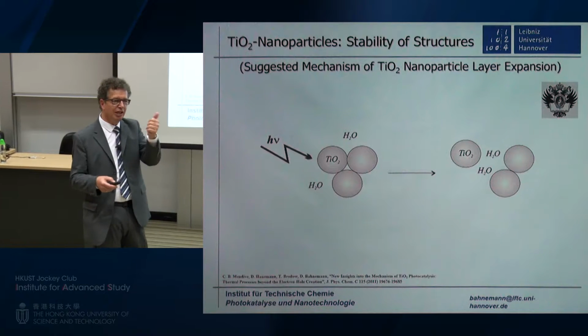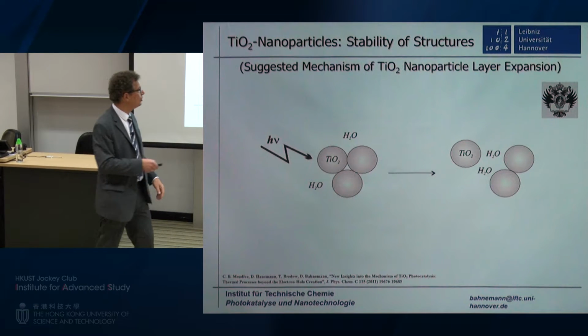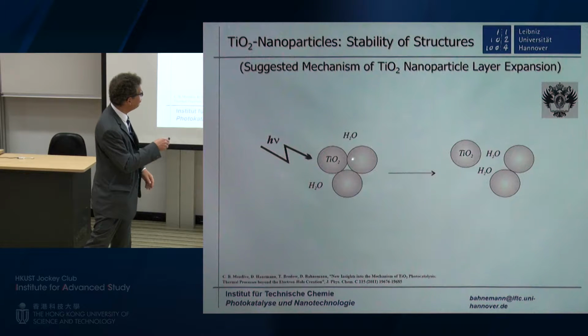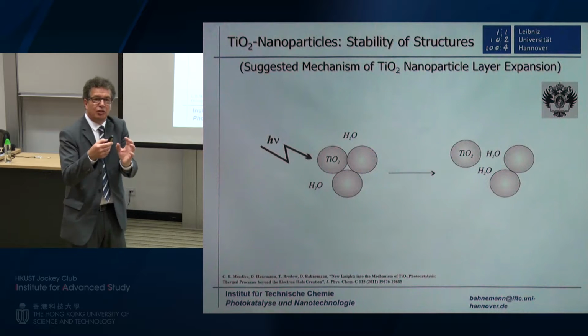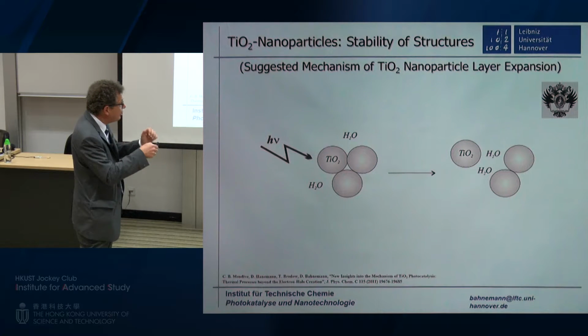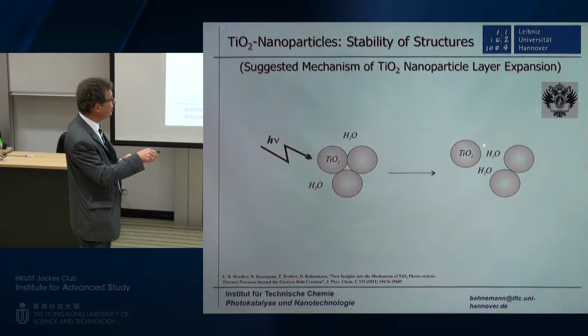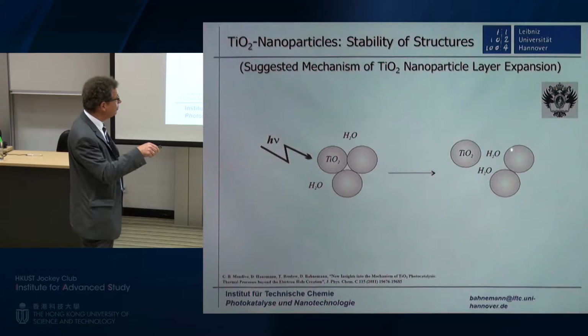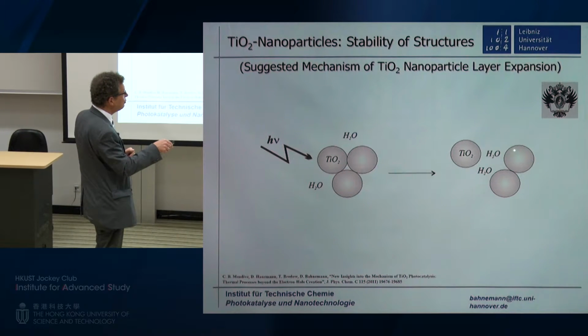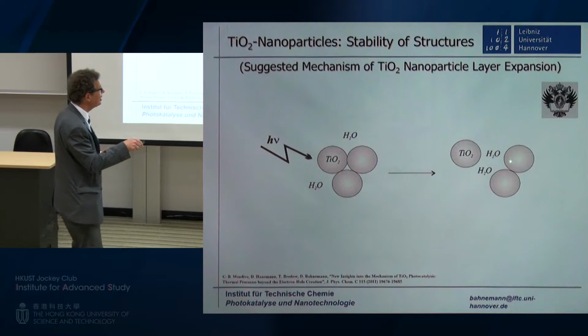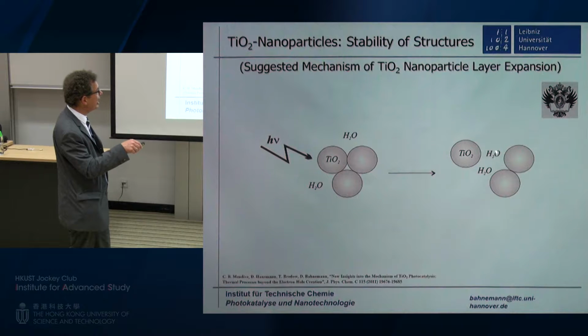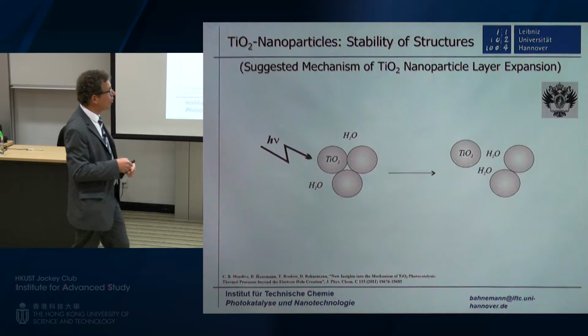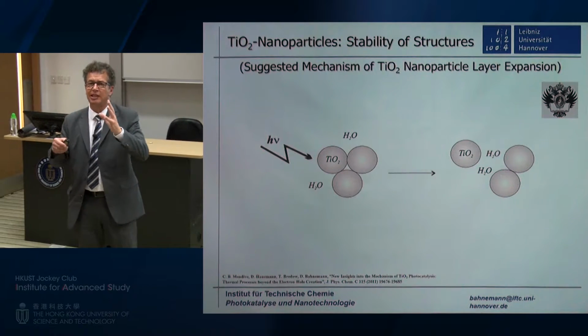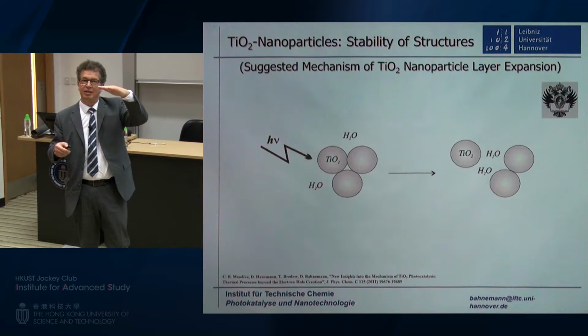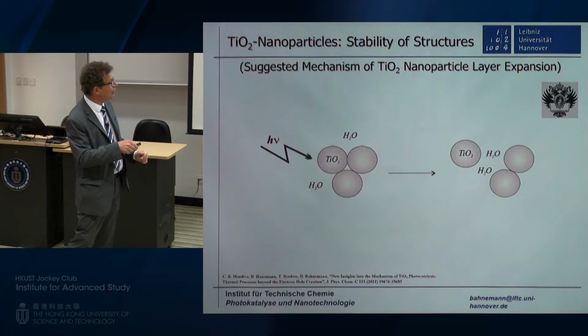3.2 electron volts, if you do a little back of the envelope calculation, is plenty of energy to break bonds, like hydrogen bonds between the particles. If you break the bonds, you turn loose these agglomerates. If they turn loose, some might actually break completely apart. Here I just show you one particle breaking apart from these two nearest neighbors, and you have additional surface area available, and this additional surface area will be available for the adsorption of water on these molecules. So if this mechanism is true, this will explain why the infrared bands showing the adsorbed water molecules rise in the system.